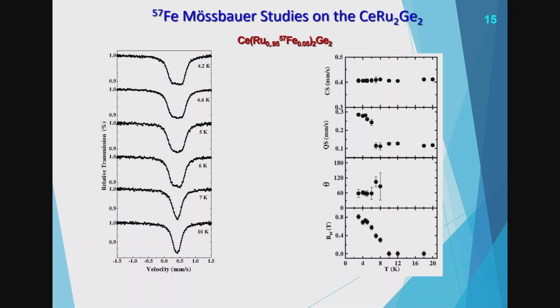And we did another sample, another material. We tested again, and we had the same problem. We made the material, and now we just put in some small amount of iron to study the pure material. And we did all the fittings going slowly in temperature. We had the same fitting, and nobody has come to a conclusion here.